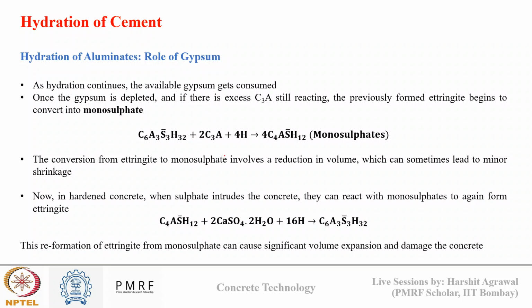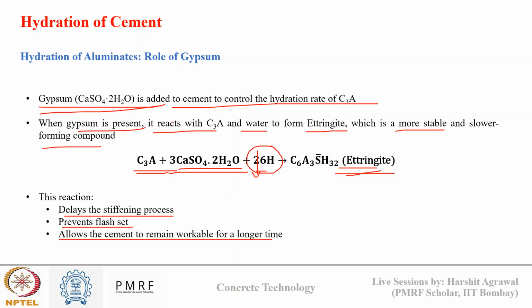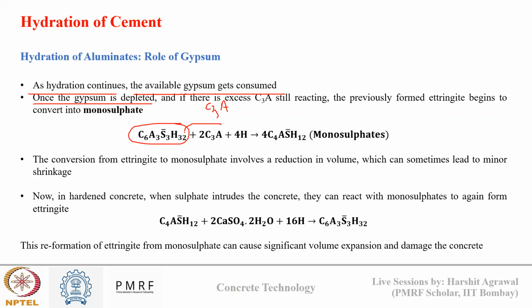However, as hydration continues, what will happen? Gypsum will get consumed. Once gypsum is consumed, if there is still C3A present in the system, the ettringite that was formed due to the reaction of C3A and gypsum will react with the remaining C3A to form monosulfate. So ettringite converts into monosulfate. It is again a calcium aluminate sulfo hydrate, but with a different composition.